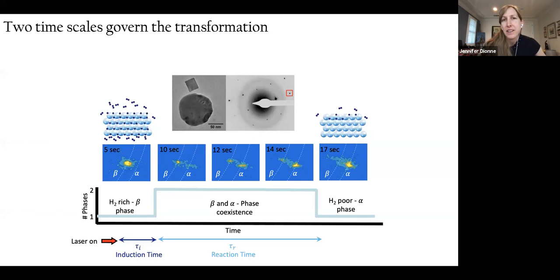So what we've learned is that there are actually 2 time scales that govern the transformation. We call these time scales the induction time and the reaction time. So if you look at the diffraction pattern and the number of phases as a function of time, like I said, we turn the laser on, initially there's a time period across which nothing happens, and we call that the induction time. And then suddenly we see the system transform from the beta phase to alpha and beta phase coexistence. And then ultimately the system transforms to purely the alpha phase. The time between when we have coexistence and when the transformation is complete is something that we call the reaction time.